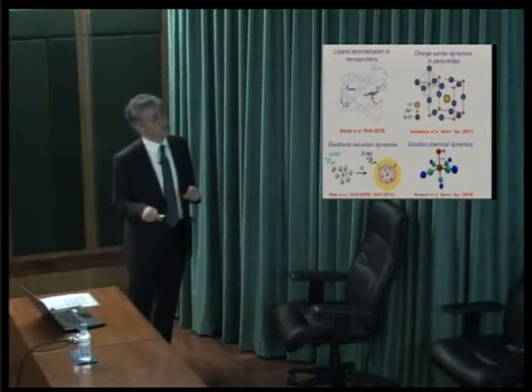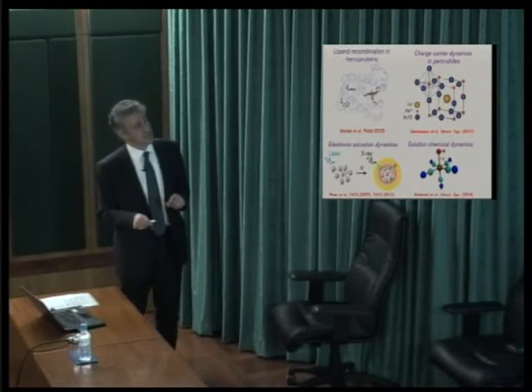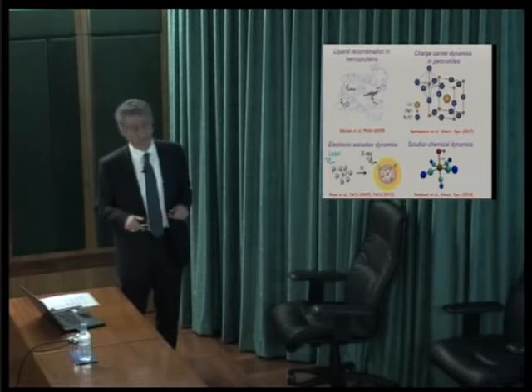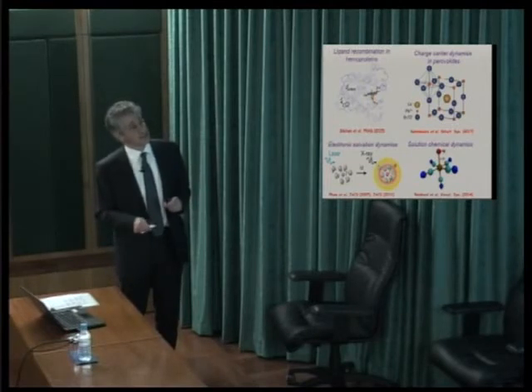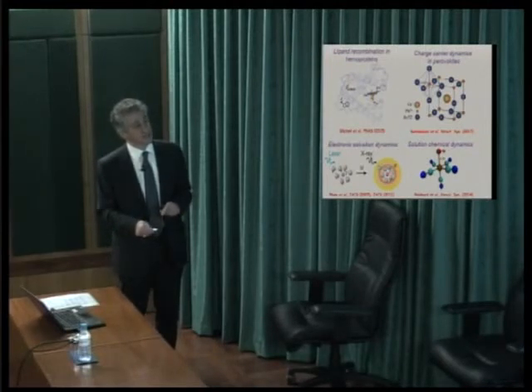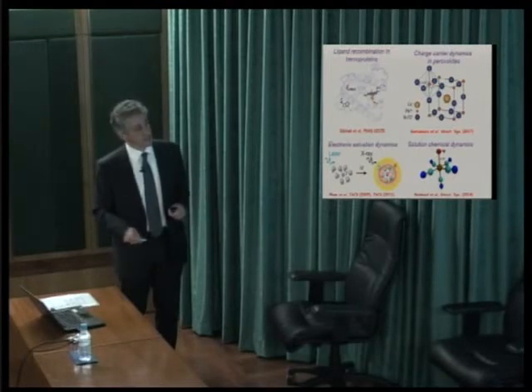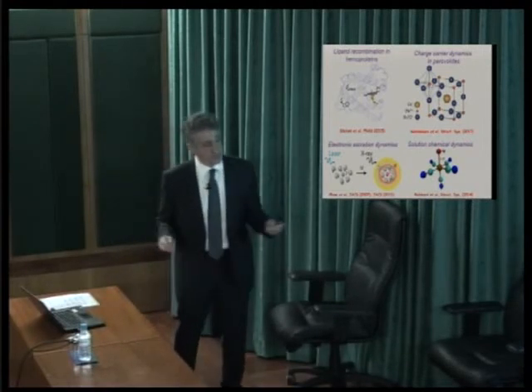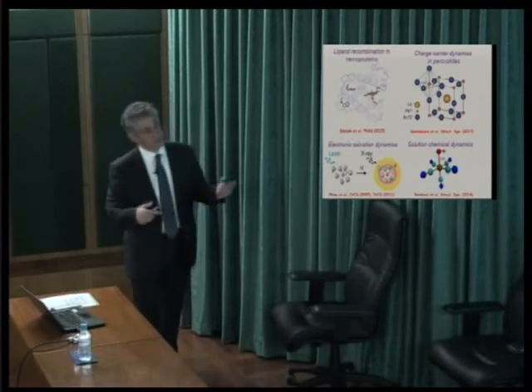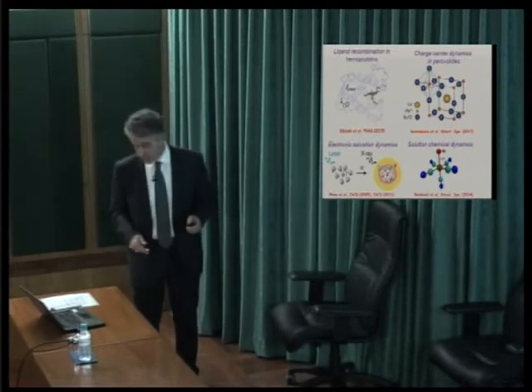We have many other results, for example, on proteins, where we looked at the dissociation of the ligand from the porphyrin and the heme, and you look at the recombination, how fast it takes place. We did first picosecond experiments here, and we have recently done experiments with a free electron laser, both in Hamburg and in Japan. We looked at perovskites by tuning to each atom, so you have element selectivity. We observed the response of the lead, of the halogen, and the cesium atoms. We looked at solvation dynamics by taking atomic solutes and changing the electronic structure of the solute by, in this case, iodide, transforming it into neutral iodine, and looking at the response of the solvation shell, which is quite dramatic. And we have also done reaction dynamics in solution between molecules and solvent species.